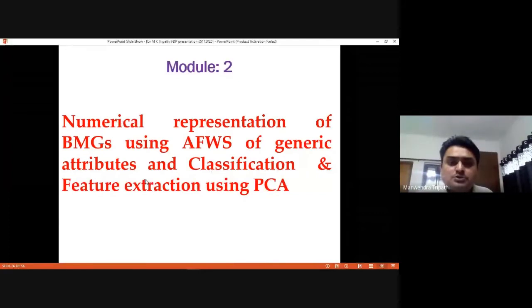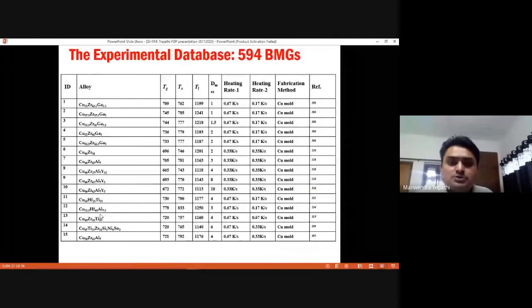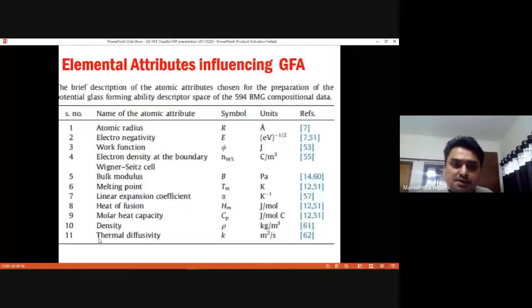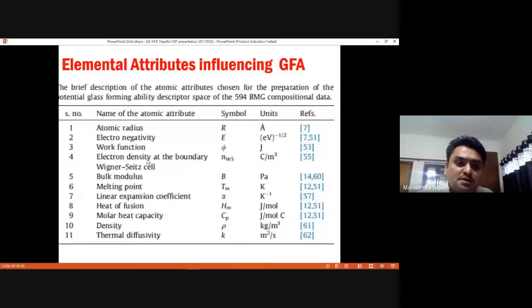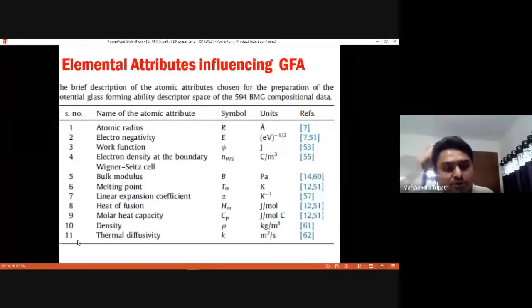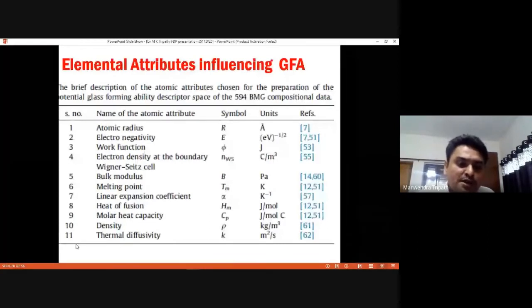So actually we cannot deal with these alloys directly. Is there any way to convert them in terms of numbers so that we can model it? So what we thought is that this slide is showing you the elemental attributes which influence GFA. It is reported in the literature that atomic radius has some role with the glass forming ability of alloys. Electronegativity, work function, electron density at the boundary of Wigner's cell, bulk modulus, melting point, linear expansion coefficient, heat of fusion, molar heat capacity, density, and other attributes. But by doing a rough set based analysis, which I am not presenting here, we have reduced it from 18 to 11. 11 such variables were taken first.